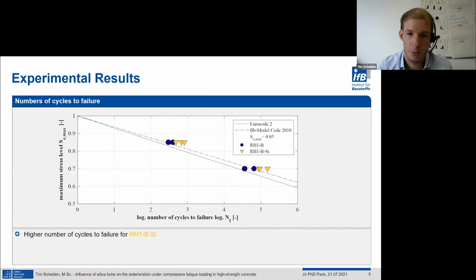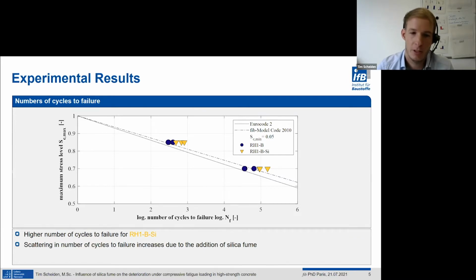So let's come to the first results. For an overall classification of the results in the context, the numbers of cycles to failure are presented here in the slide. Marked in blue is the basalt concrete without silica fume, and in yellow, the concrete with silica fume. The results show that the addition of silica fume leads to higher numbers of cycles to failure. With decreasing stress level, this effect becomes more significant. We also can see that the scattering in the numbers of cycles to failure slightly increased due to the addition of the silica fume. But in general, we can say that the addition of silica fume leads to an increased fatigue behavior, or increased fatigue resistance.